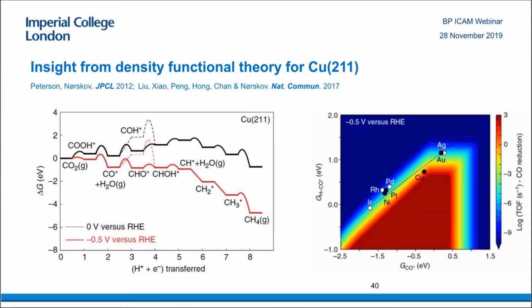However, it turns out you can't actually do that, because there's a problem. All of these intermediates bind by the carbon atom, and it turns out that their stability scales linearly with each other. The key bottleneck, as I mentioned, is going from CO to CHO. There's linear scaling between the binding energies of the different intermediates and transition states.